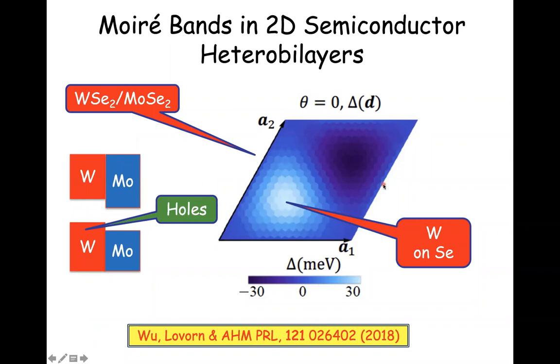For a typical twist angle, the period is something of the order of 10 nanometers. So you've basically mapped real crystal physics from the eV scale to the 10 meV scale, and from the 5 angstrom lattice constant scale to perhaps 10 nanometers or so.